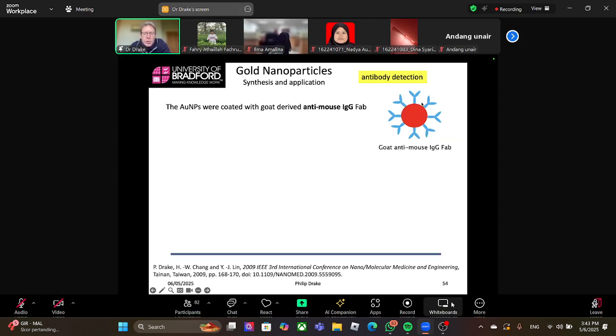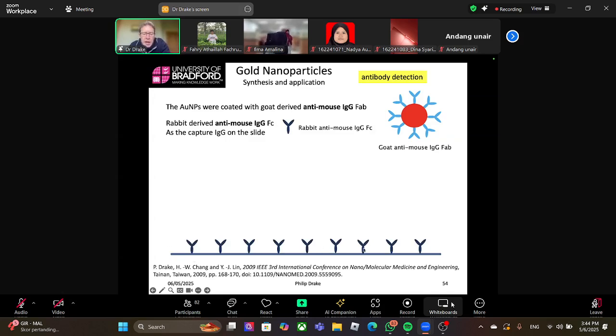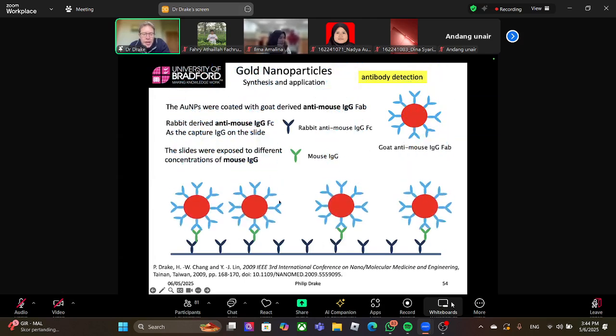So we take our gold-coated nanoparticles with some anti-mouse IgG on the surface. So these are our capture lines. This is rabbit IgG that detects mouse IgG. We add in the mouse IgG. It floats on the surface, it sticks to certain points. We then take our gold nanoparticle labels, which recognize mouse IgG. So they stick to the mouse IgG on the surface.